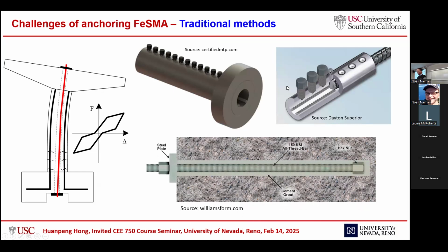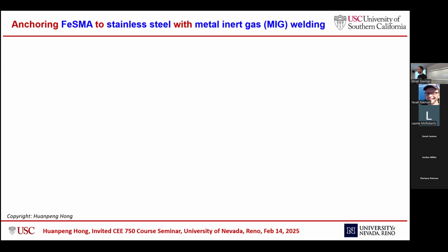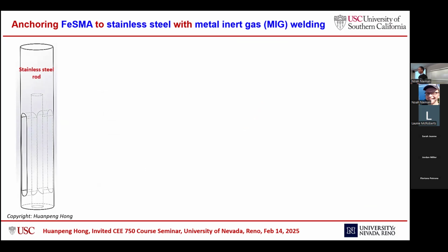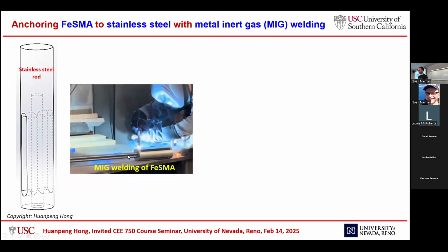These two options are okay, but the problem is that the shear screw will lead to stress concentration, and the straightening of the bar increases the cost, and this is not very flexible for on-site construction. So we started thinking about using welding. We developed a new welding anchorage method using MIG welding. We used a stainless steel rod, used machining to drill a hole in the middle and two slots on the side. If we put the iron SMA bars in the middle, we can add welding lines in these slots.